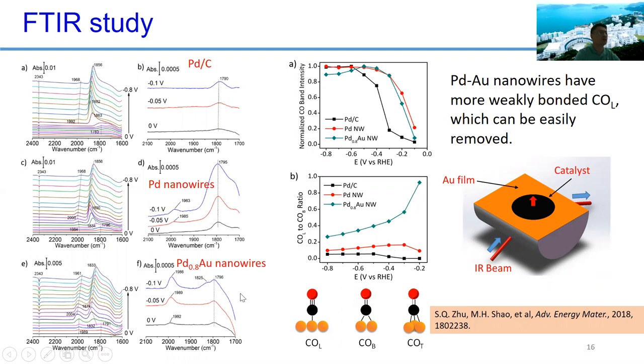So that means on the palladium gold nanowire, a lot of CO is bonded as linear rather than bridge bonded. So how does this affect the selectivity? For the linear or top bonded CO, the bonding energy is much lower than the bridge or triple bonded ones. So once you produce the CO, the linearly bonded one is easy to remove from the surface, generating CO as the final product. But the others are very strongly adsorbed on the surface, so basically they are a poison. So in the case of palladium gold, you generate more linearly bonded CO, which means the ratio will be higher.